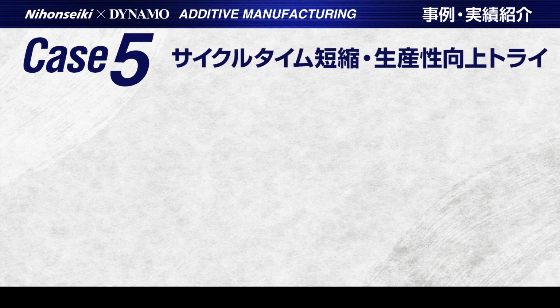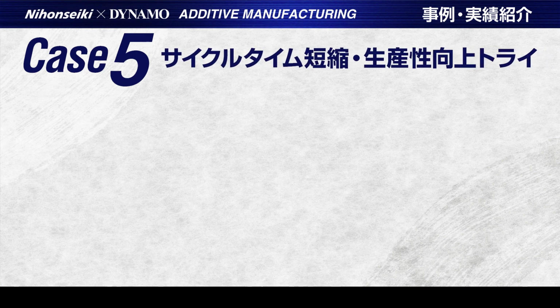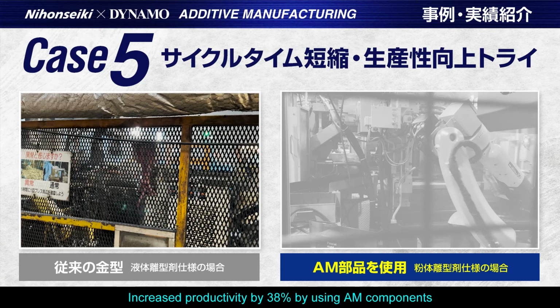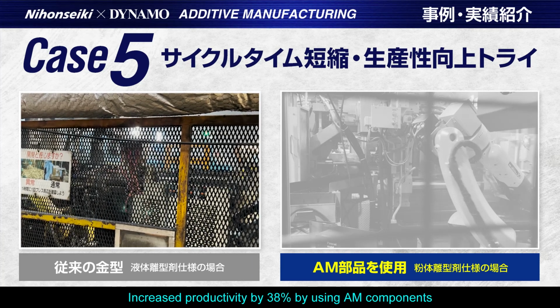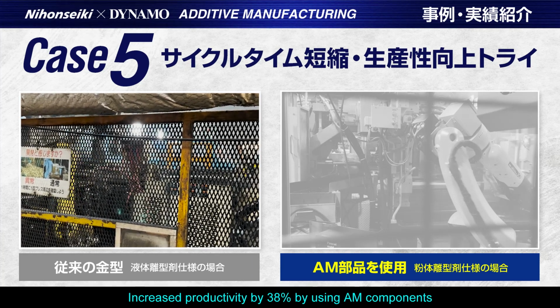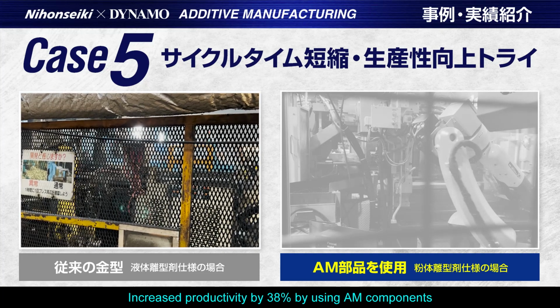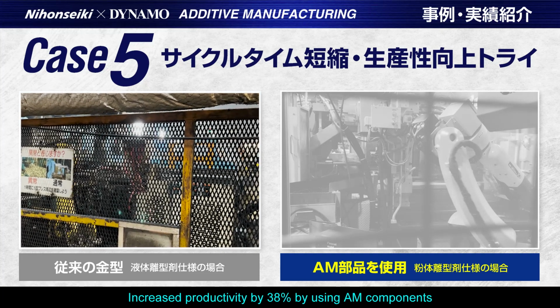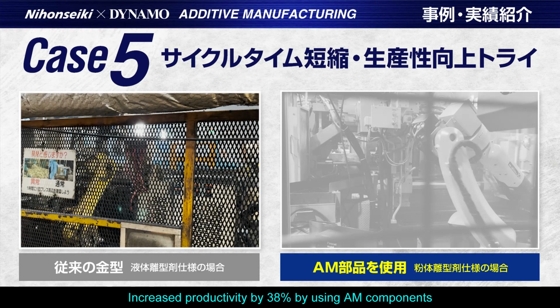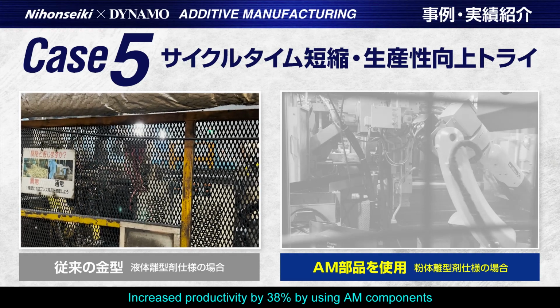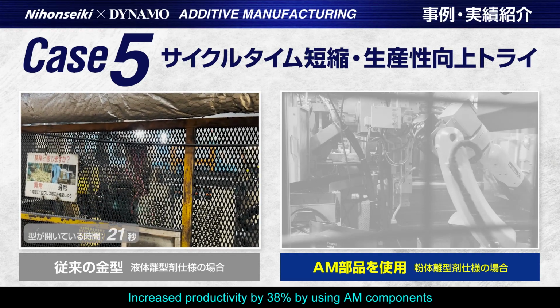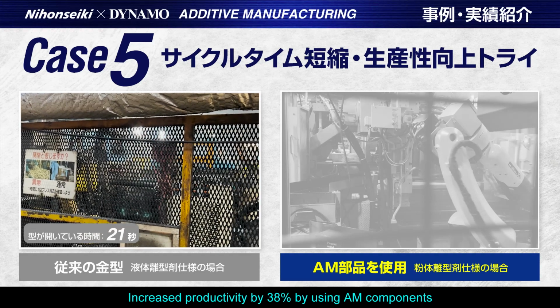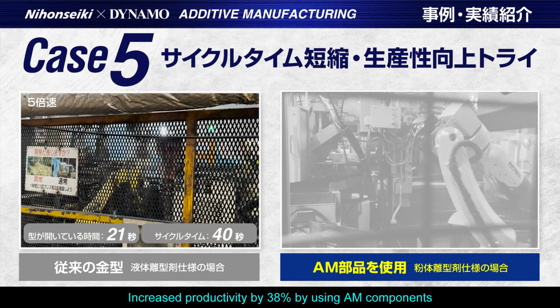Case 5. Case 5 proves that AM specification in molds contributes to shortening cycle time and improving productivity in actual casting. The left photo is a conventional mold. There is a fence which makes it difficult to see in this video. The mold release agent is being sprayed so we cannot go any closer. Due to the long process of spraying the mold release agent, the mold is opened for 21 seconds, and the cycle time was 40 seconds.